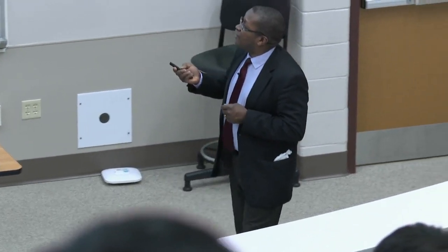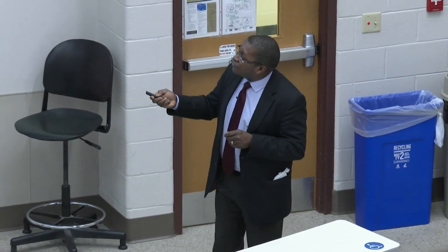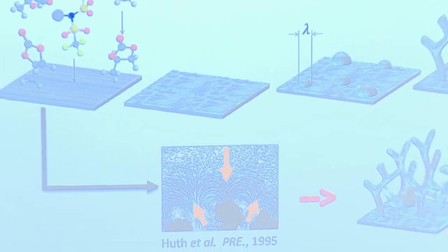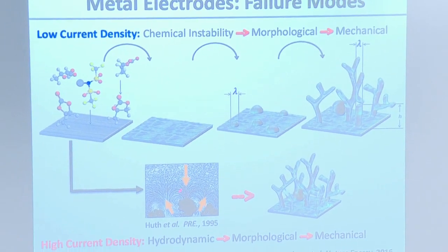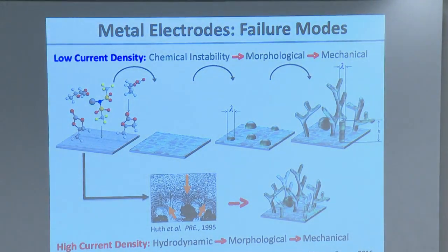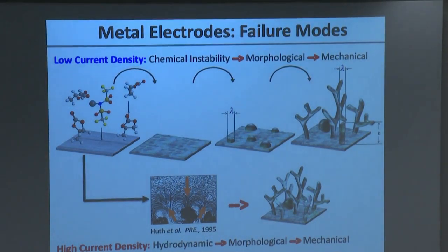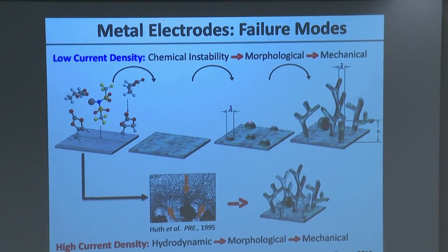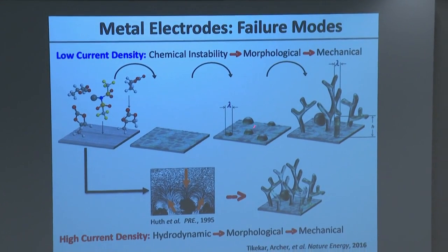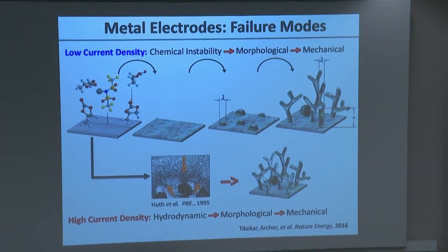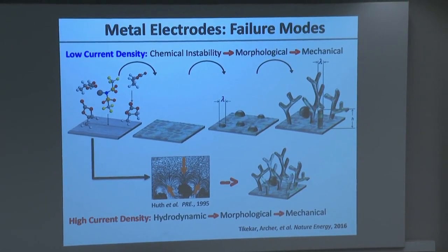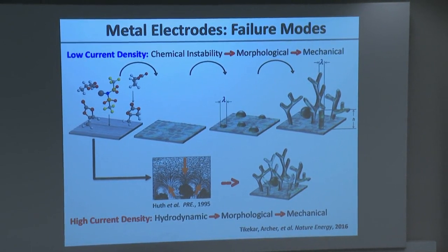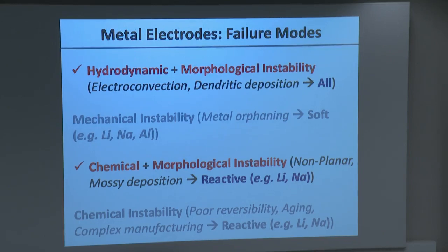And that instability in a closed cell has a certain pattern. And the pattern is actually illustrated here in this very nice work by Huth since the 1990s. It has this very nice roll cell structure where it dumps material to certain specialized spots at the interface between the electrolyte and the electrode, with the end result that you produce, not by chemistry, but by hydrodynamics, a configuration that's very similar to the one produced by chemistry, bumps that are distributed on the surface. And just as in this case, once those bumps are formed, they concentrate field lines, and off to the races, the dendrites grow. So what in the world can one do?